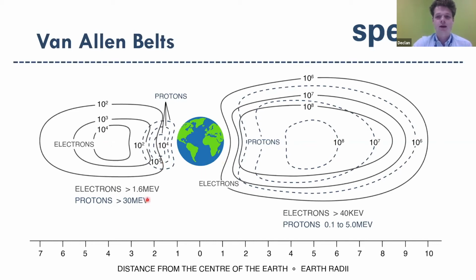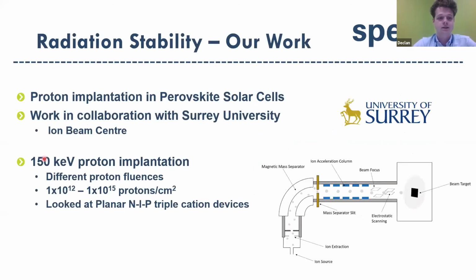Here in the inner belt, you have a much higher energy range in terms of megaelectron volts, but a much lower fluence, which is the number of protons per unit area. In the outer belt, you have a much lower ion and electron energy, but a much higher particle fluence. In the work we published in SolarRRL, we looked at 150 kiloelectron volt proton implantation.